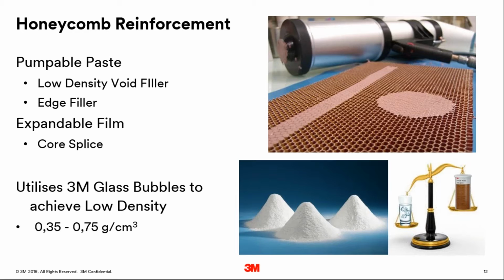These low density void fillers are available both as pumpable paste and expandable films, the films being used for areas such as core splice or edge finishing. And a key component of the low density void fillers are in fact the 3M glass bubbles that I mentioned earlier, enabling us to achieve very low densities but retaining good mechanical properties.